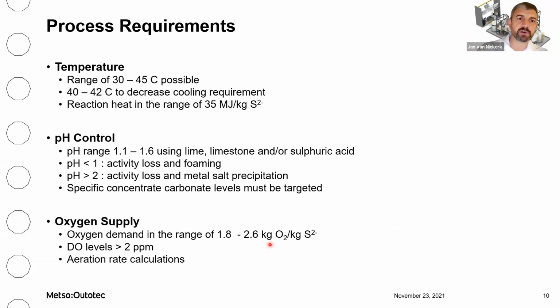The most important process requirements during bioxidation are to maintain a steady temperature in the BIOX process, to control the pH, and to ensure a steady oxygen supply for the oxidation reactions. The BIOX bacteria can operate in a range of 30 to 45 degrees. However, we normally control the process within a very narrow range of 40 to 42 degrees. The reaction heat during bioxidation is relatively high, and the design of the cooling circuit is an important engineering criteria.